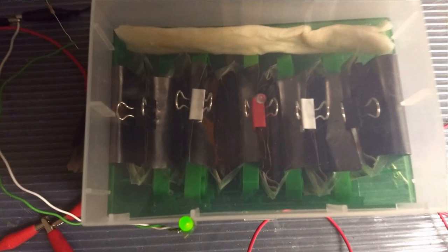The good things about this battery are it's a water-based chemistry so it's fairly safe, it's not going to catch on fire. It is fairly non-toxic, the ingredients are not going to cause problems for the people building it or for the environment. It is also not strongly acidic or basic and iron is extremely abundant.